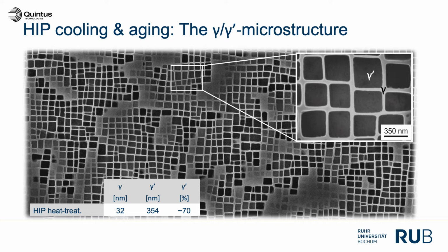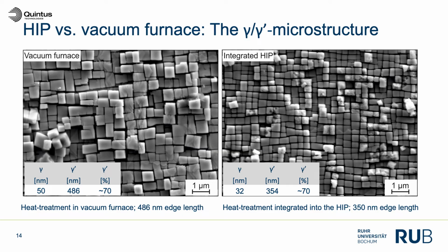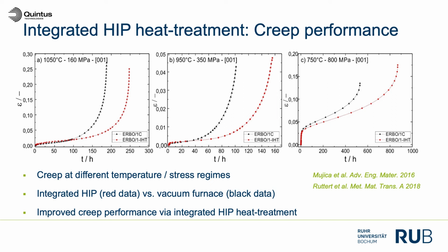And this is a bit smaller than after conventional heat treating, because then you obtain a microstructure having a gamma prime edge length of about 500 nanometers. And this has a positive effect on the creep life of the material, because a very fine and uniform gamma prime microstructure after heat quenching has a beneficial effect on the creep life, because the material deforms a little bit slower and then creep life is improved.